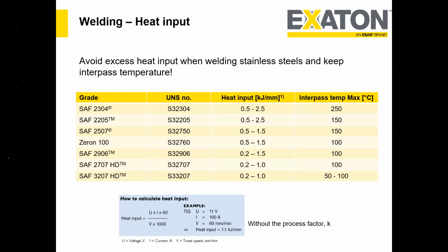And based on our experience, these are the optimum or most recommended heat input range and the maximum interpass temperature for grades like lean duplex, duplex, super duplex, and hyper duplex. So you could take this as a reference. With these references, I would say there is a 70% possibility that you will not get any kind of undesired microstructure. Why 70%? Because the other 30% depends on a lot of other factors like welder skill, your environment, your cleanliness, and many other factors.